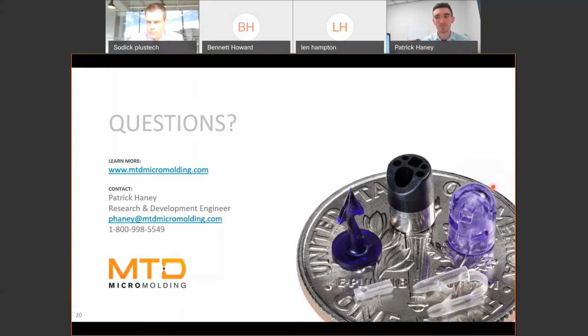So some of the limitations include equipment or just the circumstances and the nature of the manufacturing process that increase the cooling rate of your shot, right? So that as you pull heat energy out of that, your viscosity is going to raise, right? So things like, everybody wants a fast cycle time in the industry because time is money, right? So as you decrease your cycle time, you'll end up increasing your cooling rate and freezing that polymer back into a solid state faster, right? So the nature of the manufacturing process and thinking about the characteristics that influence your cooling rate are really the limiting factors.